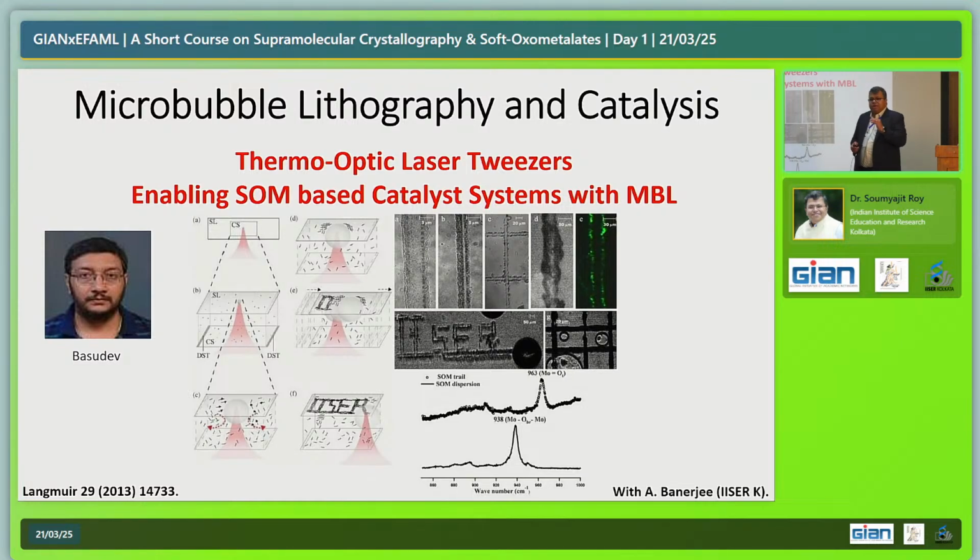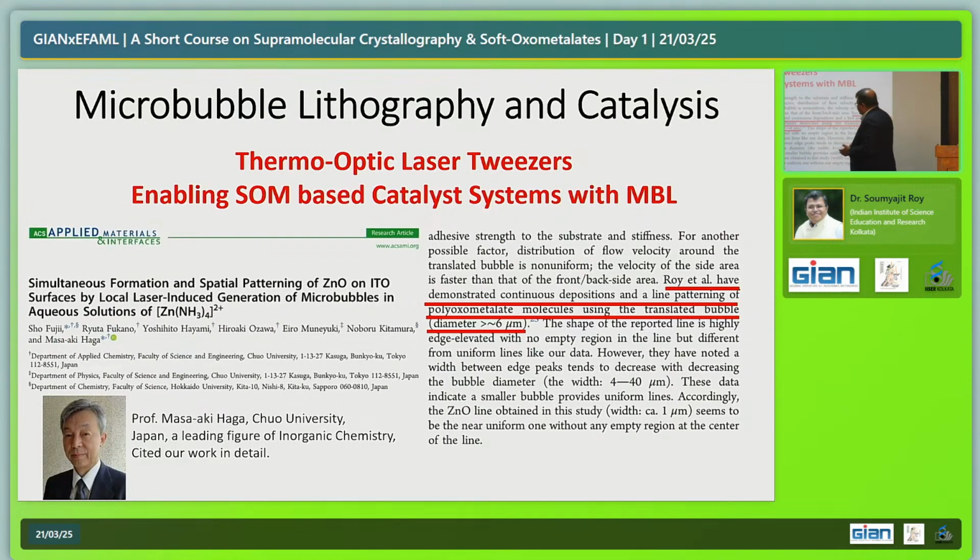But if the residence time of the bubble with the laser, the contact time or the residence time, whatever you call it, is higher, then they have more time for residence. Then you get thicker lines or thicker trails. And if you increase the time even more, you have really big dark trails, which you can even see with naked eyes. So that's kind of the power of this. So you can control the thickness or the width of these type of bubbles. And this I have shown you.